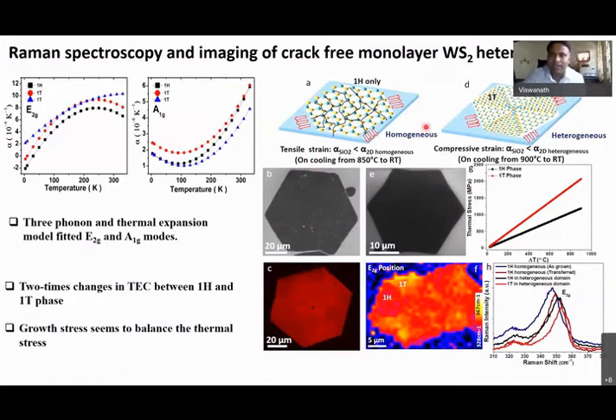One other interesting observation we had: we always think heterostructures are going to have a problem of strain. But what we found, when we have a WS2 monolayer of only one phase, in this case the 1H phase, during cooling, due to the tensile stress developed from the thermal mismatch, it is cracking. You can see in SEM extensively, it is showing cracking.